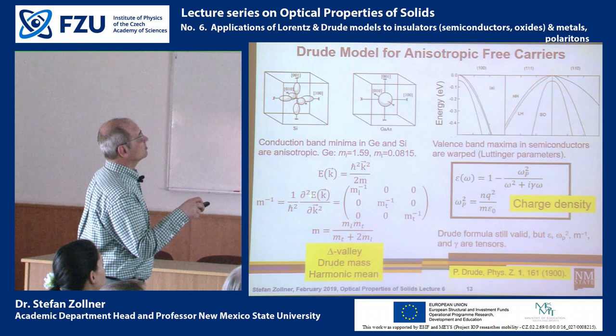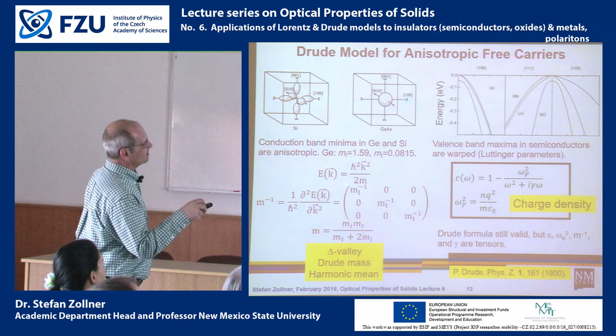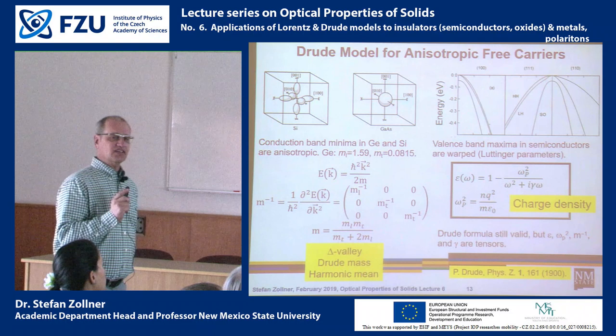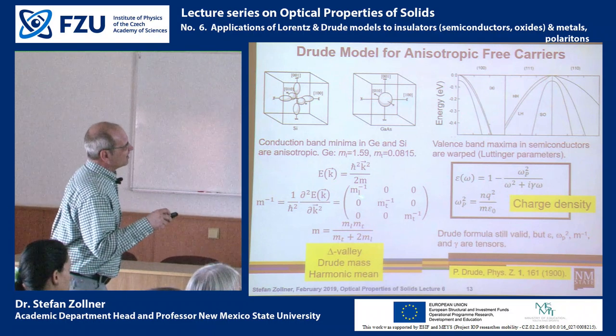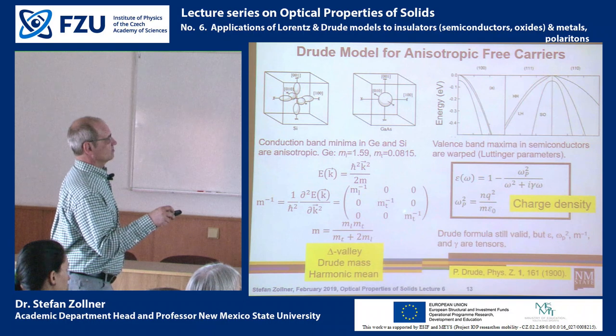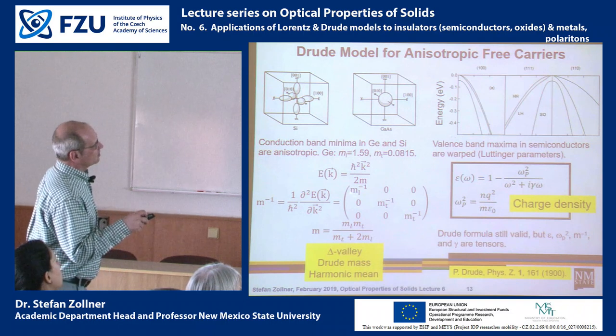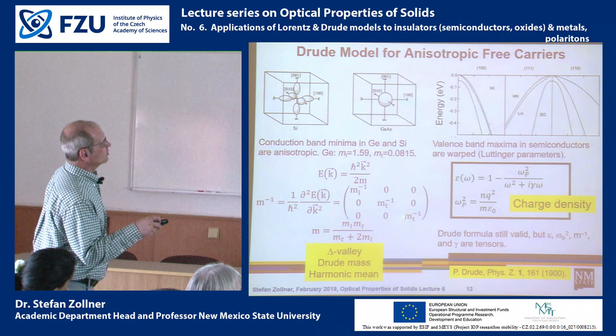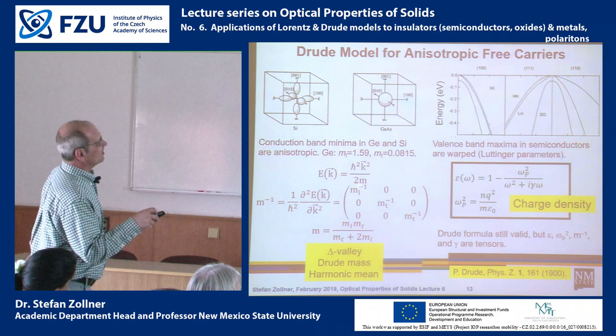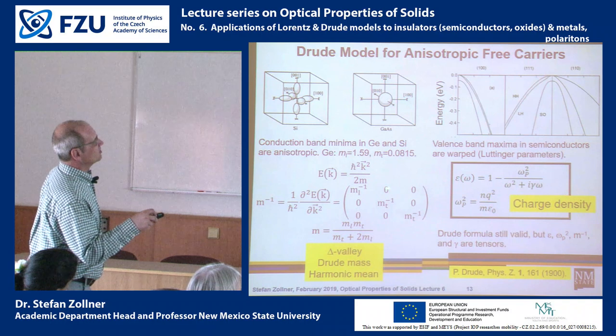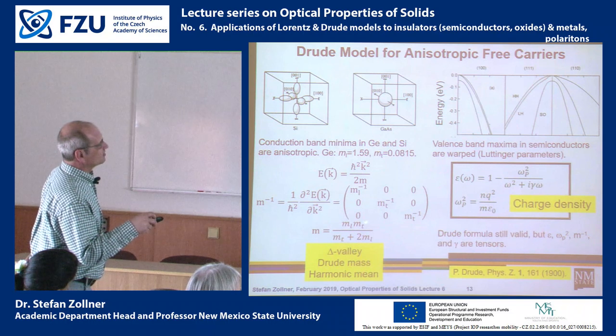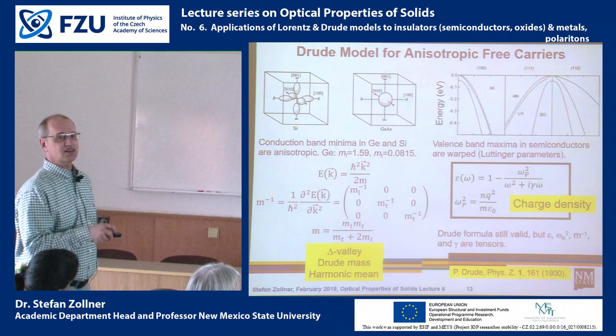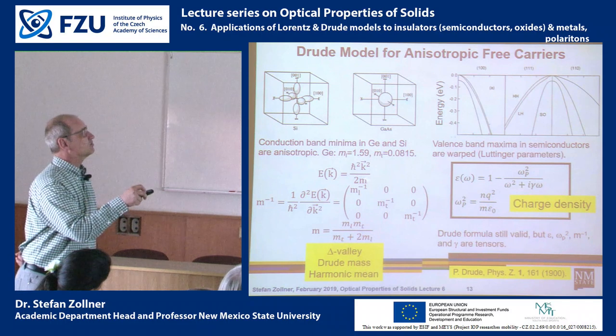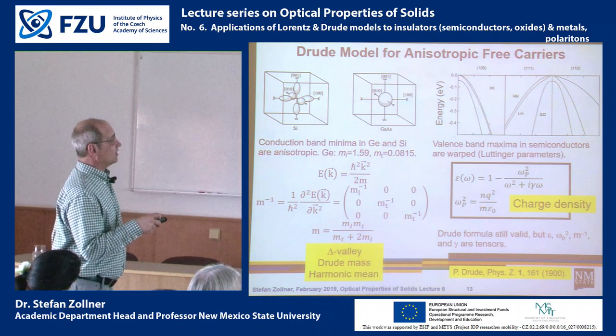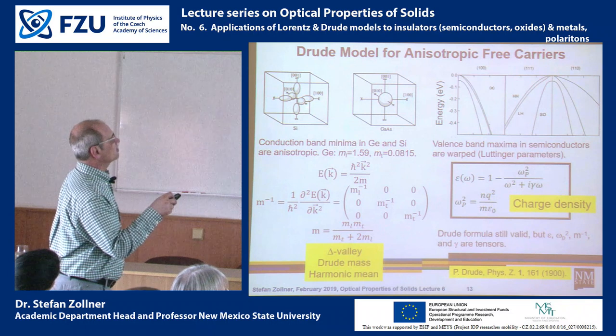So if we take this derivative for an anisotropic valley, then instead of getting the mass as a number, we are getting an effective mass tensor. And for this particular situation, where we have one longitudinal mass and two transverse masses in this effective mass tensor, the Drude mass then is equal to the harmonic mean of these three masses. So we can still apply the Drude model for such an anisotropic system.